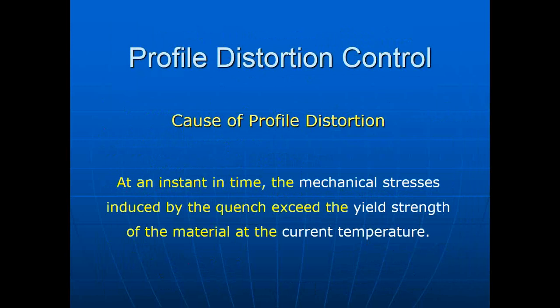How do you do permanent profile distortion? Permanent geometry distortion occurs when, at an instant in time, the mechanical stress induced by the quench exceeds the yield strength of the material at the current temperature. Now, the white words are important. Our cooling rate affects how much mechanical stress is applied, but the yield strength is at the current temperature.